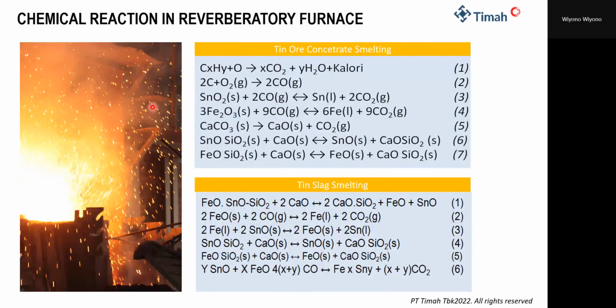And these are some chemical reactions in the reverberatory furnace. The reactions in the reverb consist of three reactions. First is burning the fuel to get the heat and energy that we need to smelt the tin concentrate, to reduce the tin concentrate into tin metal. This is the first reaction, and the second one is the reduction process. SnO2 will react with carbon monoxide. Two carbon monoxide will produce liquid tin, gas, and so on.